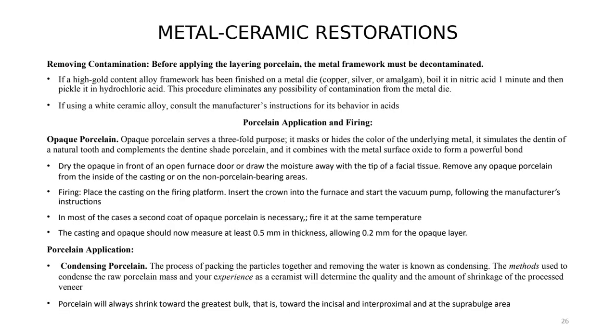Removing contamination. Before applying the layer in porcelain, the metal framework must be decontaminated. A high gold content alloy framework has been finished on a metal die, copper, silver, or amalgam. Boil it in nitric acid for 1 minute and then pickle in hydrochloric acid. This procedure eliminates any possibility of contamination from the metal die. If using a white ceramic alloy, consult the manufacturer instructions for its behavior in acids.